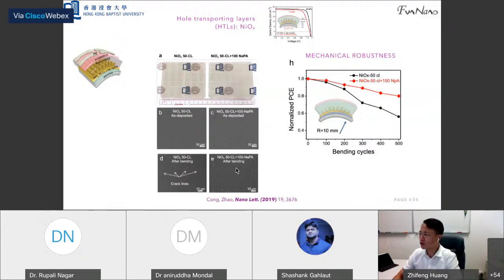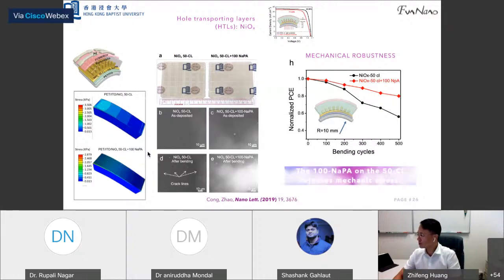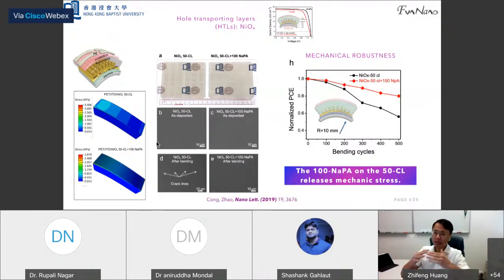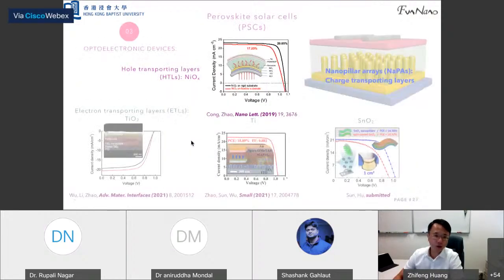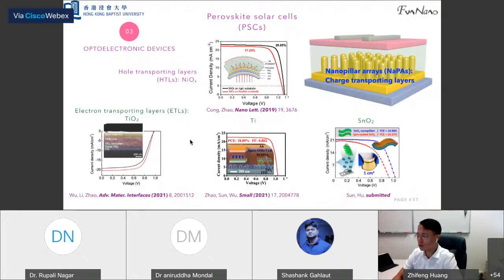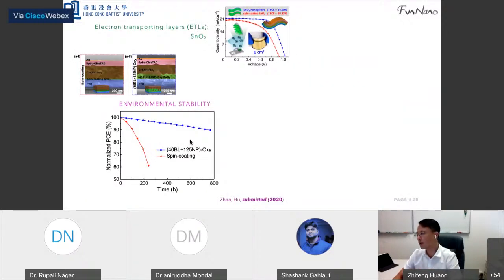And the reason is, in the sample without nanopillars, you can see the very big crack. And after the simulation, we found that the nanopillar can actually release this mechanical stress. And not only the hole transporting layers: we use tin oxide as the electron transporting layer, and we can also find this phenomenon. For example, this is the environmental stability.